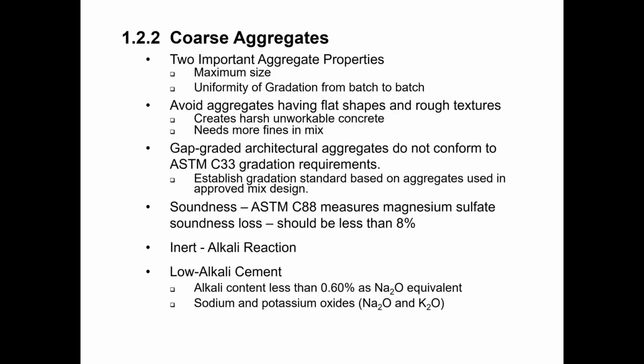Generally, we want to avoid coarse aggregates that have flat, slivery shapes, very rough textures. Now, obviously, if it is a crushed aggregate, it's going to have a rough texture, but even then, we want to avoid aggregate particles that have a flat shape or a very irregular shape, because that can lead to a very harsh concrete mixture that does not perform well with regard to slump and workability.